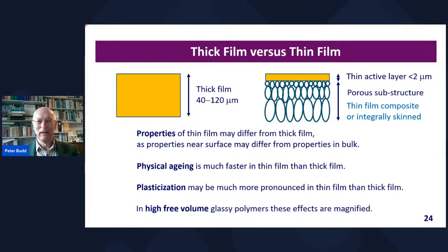But of course, if we're talking about a commercial membrane, then you always want your active layer to be as thin as possible to increase the permeability, to increase the flux, the amount of stuff that comes through the membrane. And a very, very thin film obviously isn't mechanically strong enough to stand by itself in a pressurized process or anything like that. So it has to have a substructure to give it mechanical support. And this can be brought about in different ways.